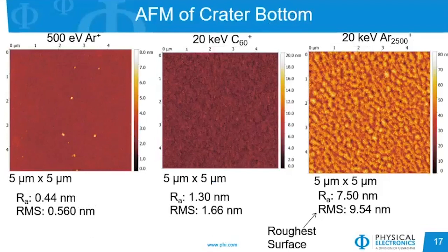So related to what we have seen about interface quality, we can look at the crater bottom with atomic force microscopy to understand how that may affect it. This is a 5x5 micron area at the crater bottom of the three different samples that we've looked at with these three different ion sources. We find that the monoatomic argon has the lowest root mean squared roughness, whereas the argon gas cluster has the highest roughness. And so that may be related to why we see broad interfaces. If a rough surface prevents us from adequately sputtering away material in our sputter cycles, then we could see distribution of those materials across layers.